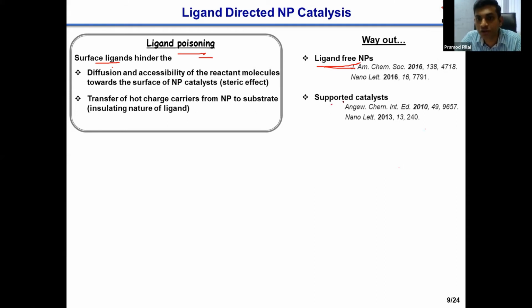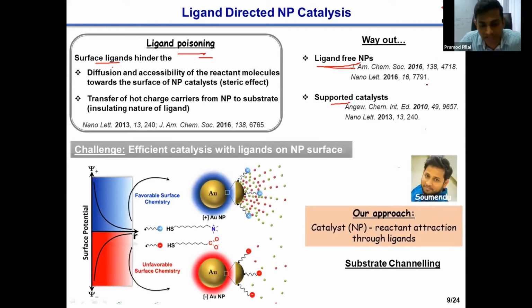The other way is to do supported catalysis, where you take a nanoparticle and you support it onto a two-dimensional surface like graphene or zinc oxide or TiO2 and perform the catalysis. This is again a very attractive strategy, but here the problem is that only a portion of the catalyst is available for the catalysis, because a big portion of the catalyst is getting adsorbed to the surface and only half of the surface is available for catalysis. So the ideal way in the area of nanoscience is to perform catalysis with ligands on the surface of the nanoparticle. And this is the biggest challenge in the area of nanoparticle catalysis.